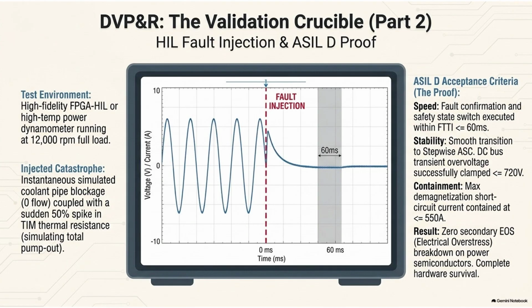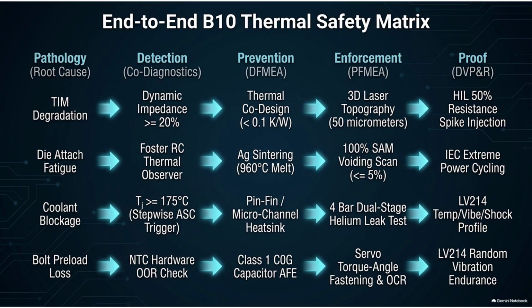Let's look at the first test outlined in the protocol, the Power Cycling Extreme Endurance Test. Based on international IEC and AQG standards, they put the module on a test bench and blast the chip with massive phase currents, intentionally forcing the internal temperature to fluctuate by greater than or equal to 80 Kelvin in seconds. They're artificially inducing that brutal thermal-mechanical stress, the CTE mismatch tug-of-war we talked about, on an accelerated timeline. They want to break it. They want to force the silver sintering to fail. And they don't just do this a few times. They pulse that massive heat 100,000 to 200,000 times continuously.